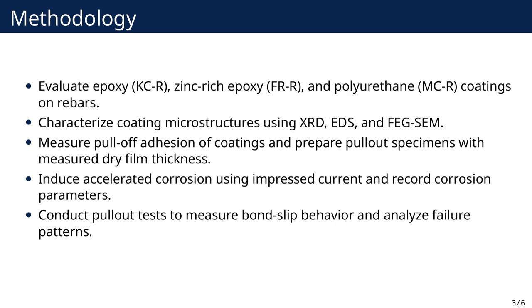Three rebar coating systems were evaluated: a conventional two-component epoxy KCR, a zinc-rich epoxy FRR, and a moisture-cured polyurethane with micaceous iron oxide MCR. Concrete mix proportions were standardized using ordinary Portland cement, river sand, and 10 mm nominal size coarse aggregate with a water cement ratio of 0.3.